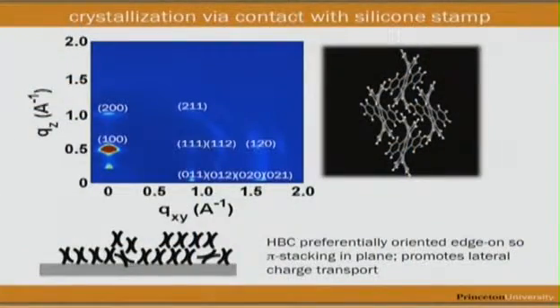Okay? So what happens when you look at the film that's been crystallized against a silicone rubber stamp? Well, the X-ray pattern looks very, very different. Instead of rings, what you see are spots. The spots indicate that the film is highly oriented. So the molecules are very, very oriented. And again, by doing that same analysis, what Anna figured out is these molecules are actually oriented edge-on. Okay? So when they're oriented edge-on like so, their pi orbital overlap direction is in the lateral direction, and that's in the same direction as you would like to transport charge for thin film transistors. So it's no wonder that these films exhibit high mobility.